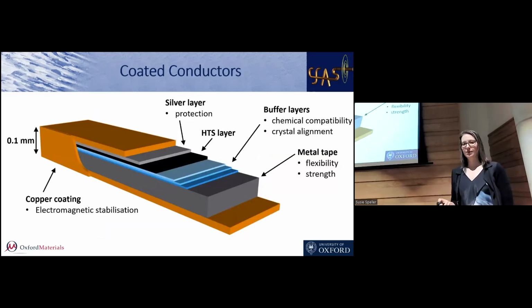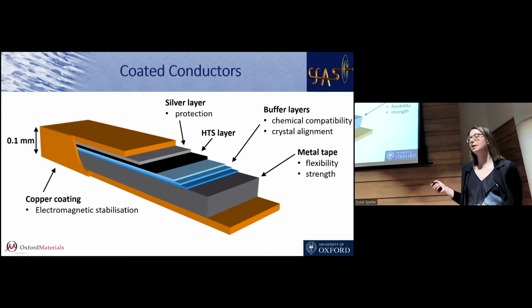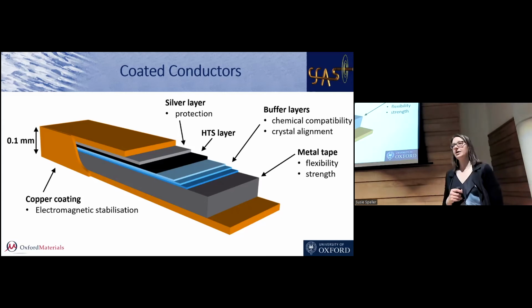Well, we start off with a metal substrate, a bit of ribbon that's metallic. That's this layer here. And we grow layers on top of it of all sorts of different things, different oxide materials mainly, one on top of the other. And then we put the superconductor layer in, very thin, about 1 micrometer, which is about a millionth of a meter, about 1,000th of a millimeter in thickness. And then we put some silver on the top and we coat the whole lot in copper, usually. And that makes us a nice flexible tape.